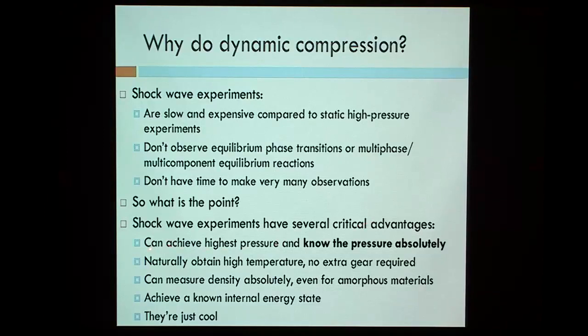First of all, you can get to the highest pressures. You cannot, by any static compression mechanism that we have available to us today, get beyond about 5 megabars, absolute limit of what you can do with diamond cells or anything. It's becoming routine to do shockwave experiments in the terapascal range. I'm sorry if I switch between bars and pascals. But with something like the National Ignition Facility, 192 gigantic lasers aimed at a small target,